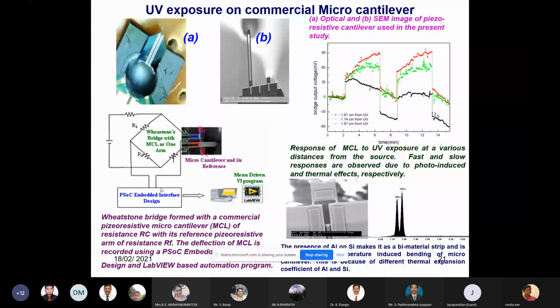We purchased a commercial cantilever. Then we saw it is a piezoresistive cantilever, so we formed a bridge. Then we exposed the tip of the commercial microcantilever to UV. We are able to get the right-hand side graph, with three different colors for three different distances of the UV lamp. This is the initial, first-level measurement.